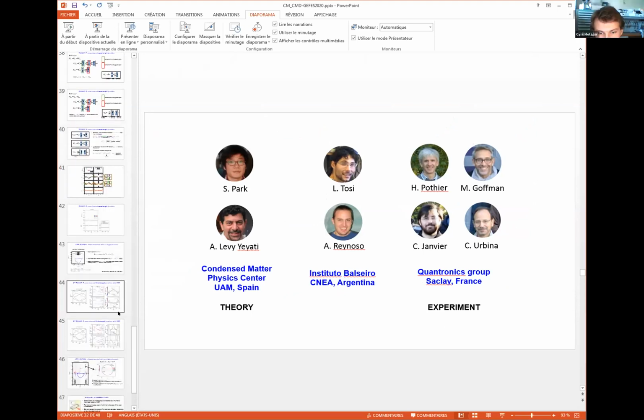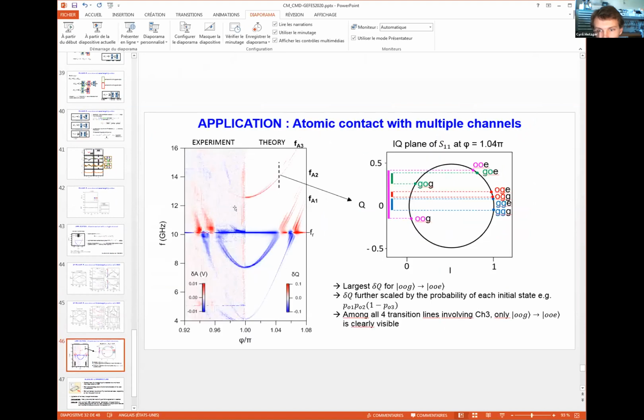In this case, maybe I can tell you a bit more about this spectrum, which was quite interesting. So you see that actually Andreev transitions were split. And this is actually an effect from the inductance of the loop. Because of the screening currents in the loop, the phase drop across the junction is not simply given by the reduced flux, but you have to take into account the current that is circulating. And so for a given value of the flux, the phase across the junction depends on the current circulating and so on the exact frequency of the Andreev bound states.